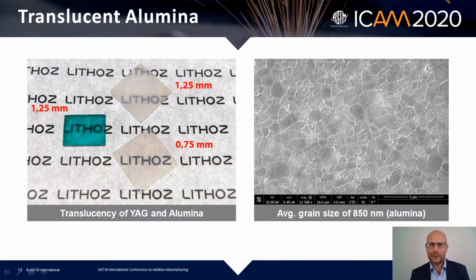I think also what's very important to show the quality of additive manufacturing is if you can make alumina translucent. Which means that if something is translucent, there can be no pores included, there can be no cracks, everything needs to be perfect, and this is what we could show. So here you see two different aluminas, two different thicknesses, and you can clearly read through it. And also on the left-hand side, the green one is a YAG material, where you can also see that you can read through that.